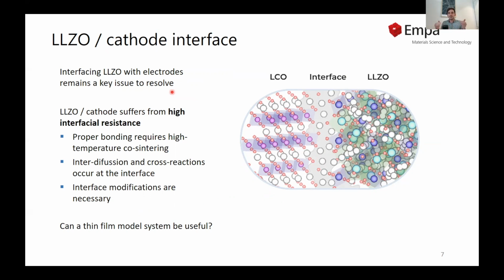And this leads to interdiffusion processes and cross reactions that occur at the interface and form an ion blocking interface. Therefore, it becomes necessary to do some interface engineering to prevent such a cross reaction process. And our question was, could we use a thin film model system to better understand the degradation process occurring at the interface and to use this system as a playground for interface engineering?